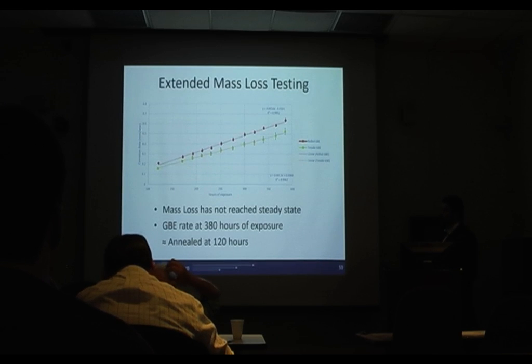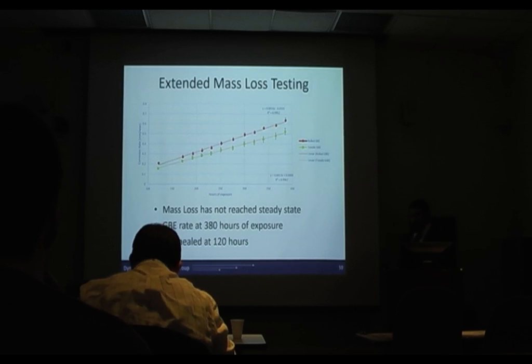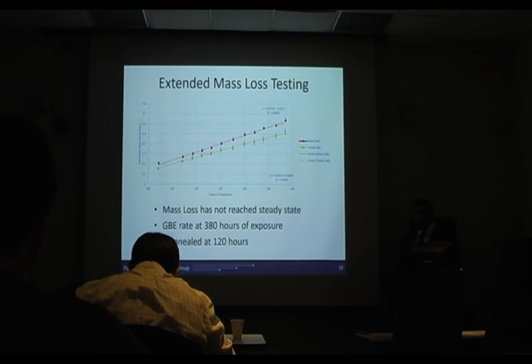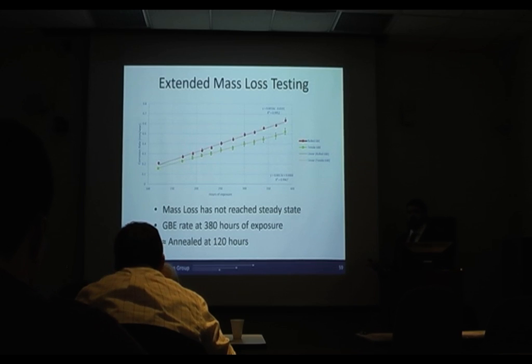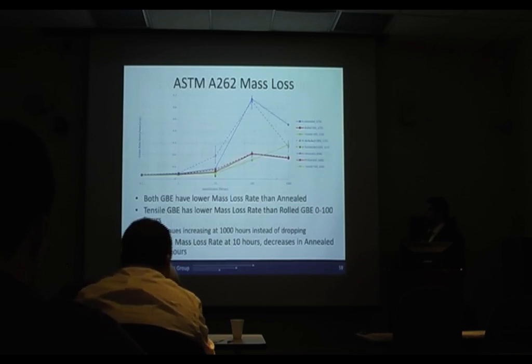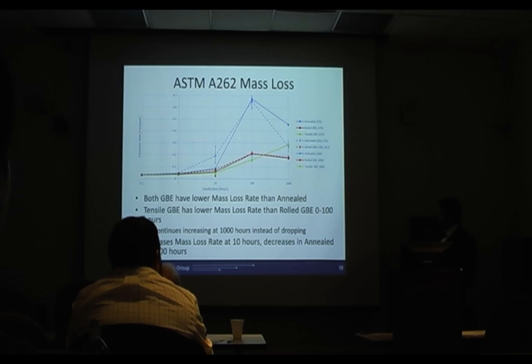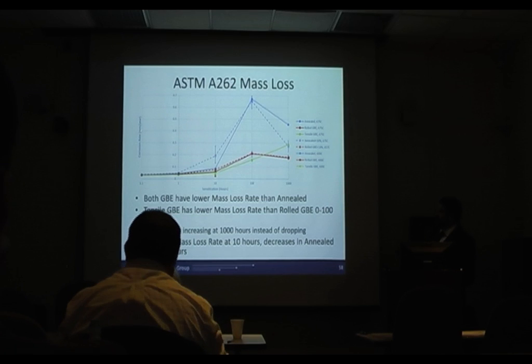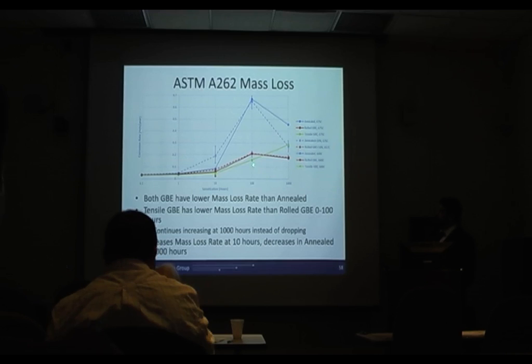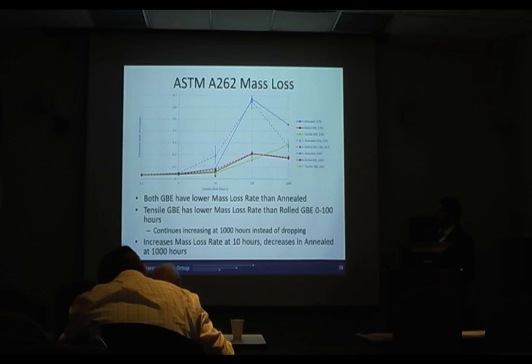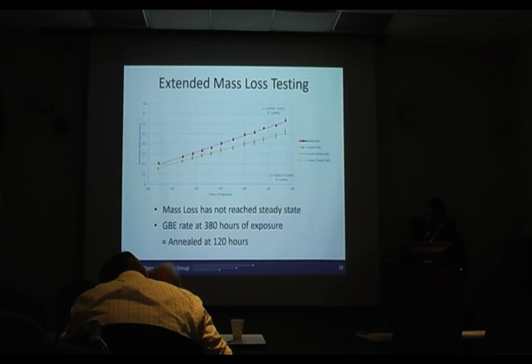Now, one of the questions I had was, will these twin-related domains ever drop out? So I took, on slide 58, the 100 hour sensitized, the two rolled and tensile GBE conditions that are much better than the annealed. I took those and put them back in. So this is sensitization time versus mass loss, and in the next one, we're looking at exposure time instead. So it's the same samples, just put back in the bath for longer, same sensitization.